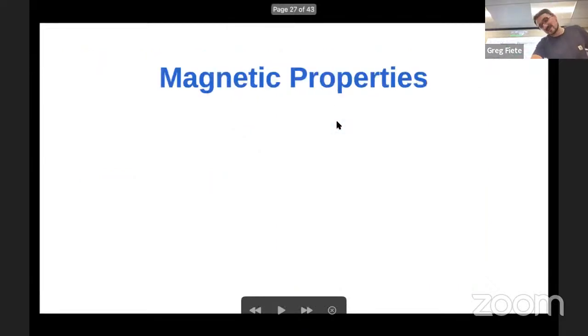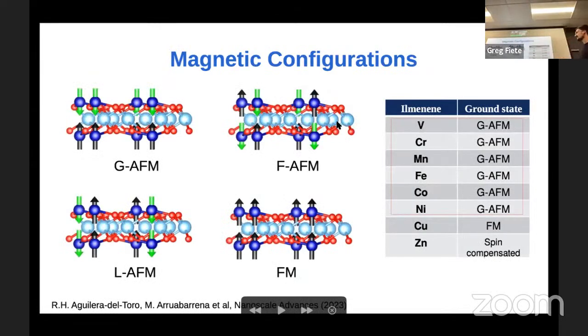Okay, after looking a bit at the structure, we once again move to the magnetic properties, where you can consider a lot of different magnetic configurations. Here I show just some of them. We have once again the GAFM, an antiferromagnetic bilayers structure with ferromagnetic planes antiferromagnetically coupled; the FAFM, where both of the couplings are antiferromagnetic; the antiferromagnetic bilayers; or even the fully ferromagnetic. But in short, for almost all of the transition metal ilmenenes, the GAFM structure is the magnetic ground state, except for copper, which was ferromagnetic, and zinc, which, being spin compensated, is not magnetic.